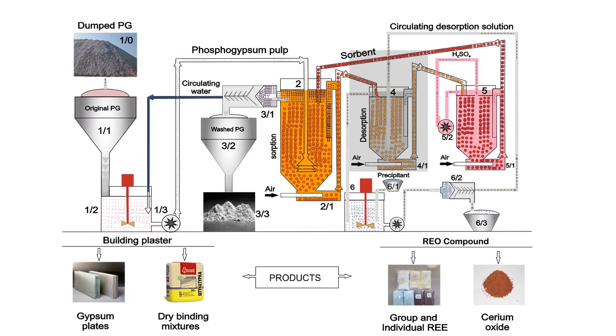At the fourth step, desorption of REE is carried out. For this, saturated sorbent from the column, position 3, enters from above into the desorption column, position 4, and the desorption solution through the distribution column is continuously fed down the column 4. Desorption of REE is carried out at counter-current flow of desorption solution and sorbent, respectively solution bottom-up and sorbent top-down of the column.